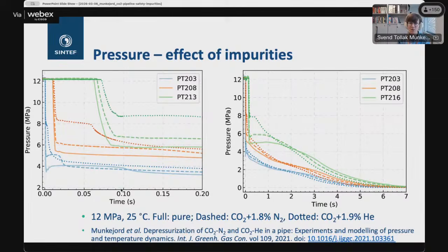So if you look at the left-hand plot, there are 3 positions at which we measure the pressure. So the blue is close to the outlet, and the 2 others a bit further upstream. There are 3 different fluids here. So the full line is pure CO2, the dashed line is CO2 with nitrogen, and the dotted one is CO2 with helium. And you can see, looking at the green one here, for instance, the pressure drops later with CO2 helium. This means that the pressure propagation speed, or speed of sound, if you will, is slower in the mixture. It also levels off at a higher level, which means that this mixture boils at a higher pressure, as you also saw in the phase diagrams.